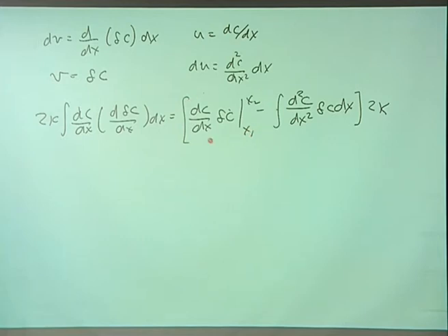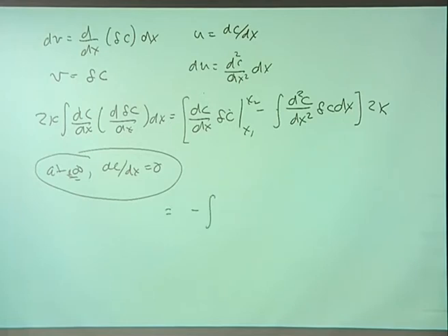Because what we're going to do is say we have an infinite system, and we're going to neglect these terms. So we're going to say that in infinity, dc/dx equals 0, at plus or minus infinity. So we're just basically going to neglect those terms. You can write this as follows, but you have to keep in mind that when you do interfaces, or when you do surfaces, you have to include those terms. You can't neglect them like what we do in the classical theory of spinodal decomposition.